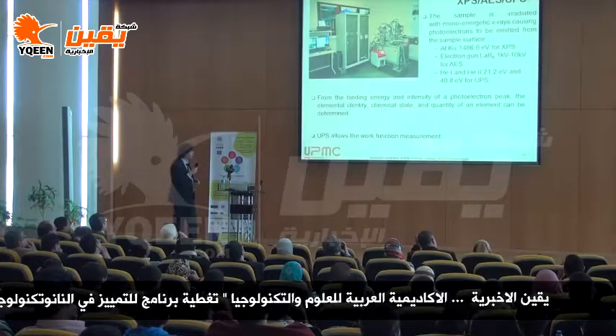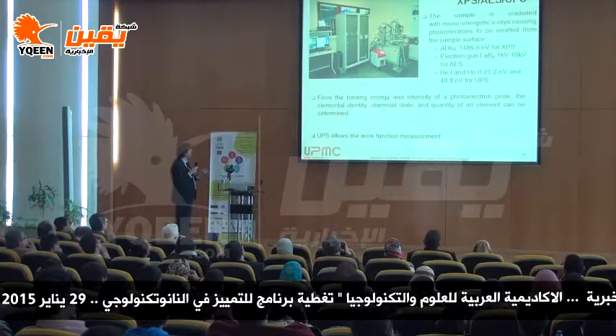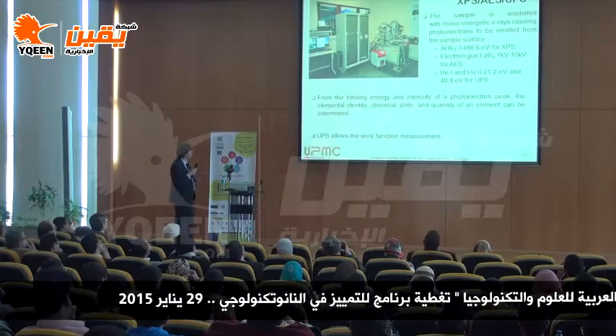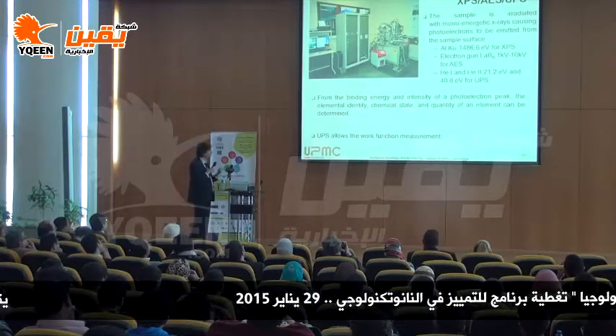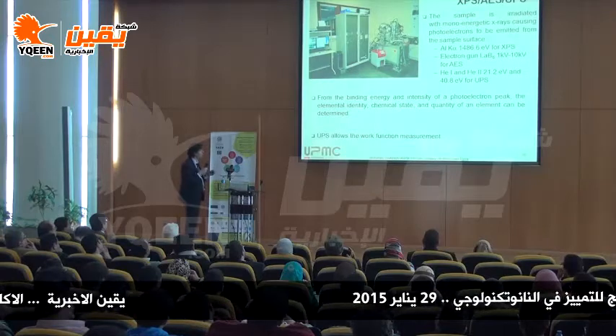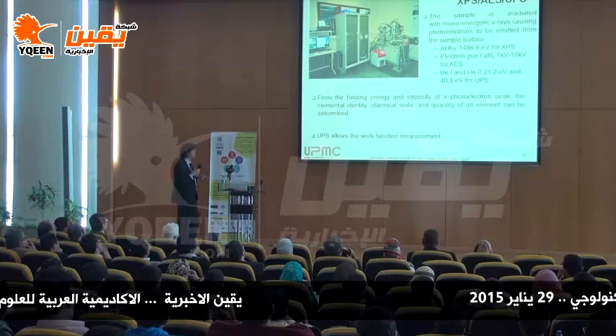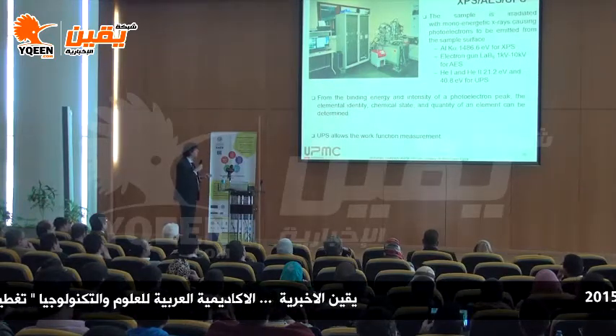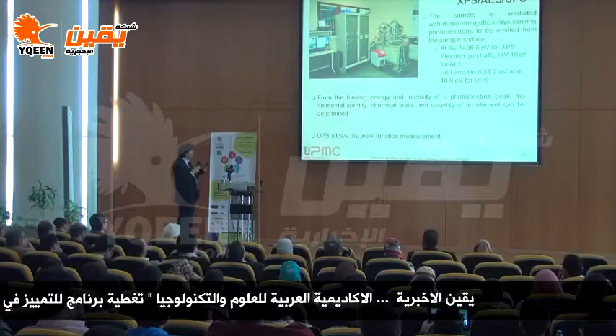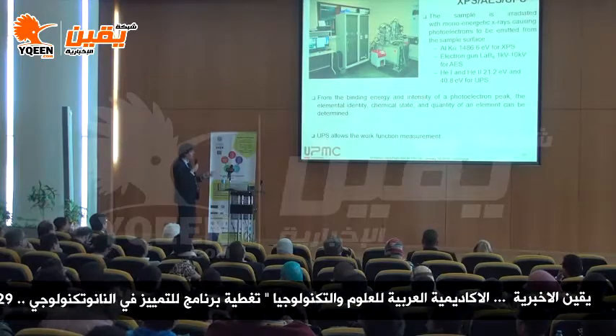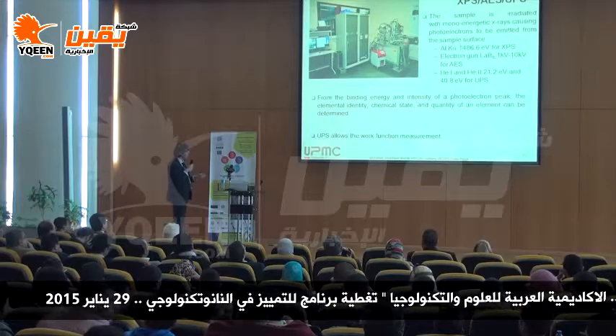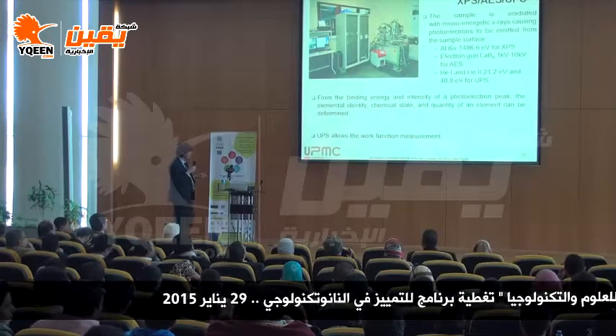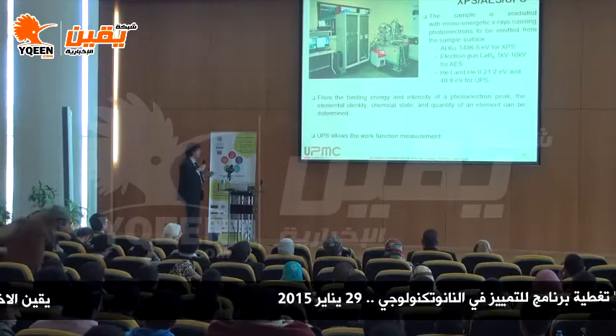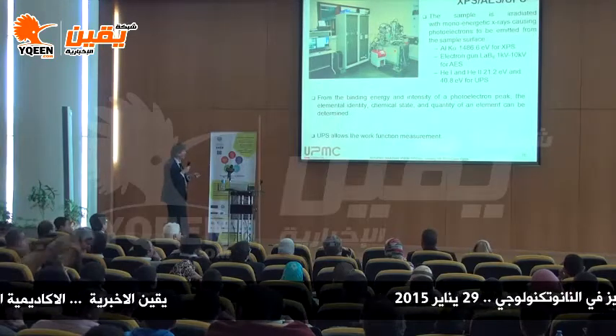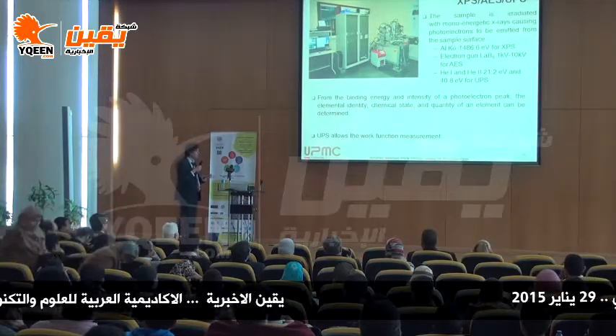Spectroscopy, so photoemission spectroscopy system. This platform is unique in France because it gathers X-ray photoemission spectroscopy, Auger electron spectroscopy, and ultraviolet photoemission spectroscopy. So here we shine dedicated energy onto the sample, and from the binding energy that we measure with the detector and the intensity of the peak, we collect the elemental identity, chemical state, and also the quantity of the